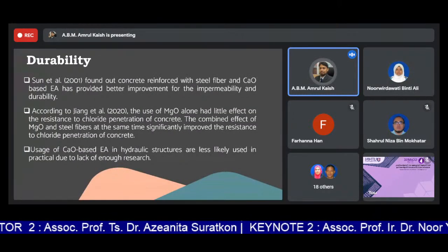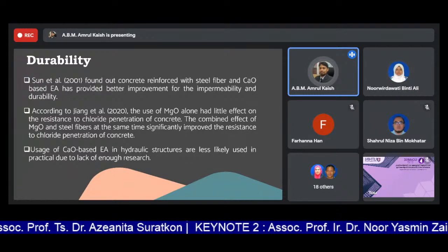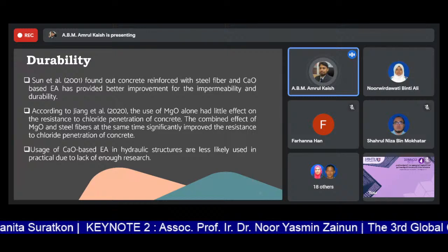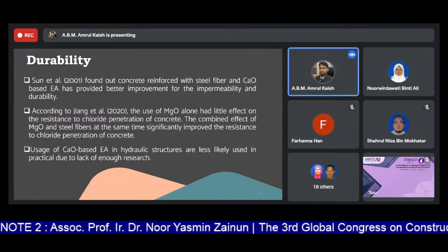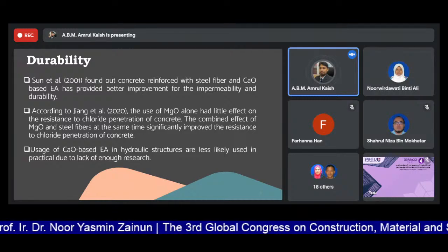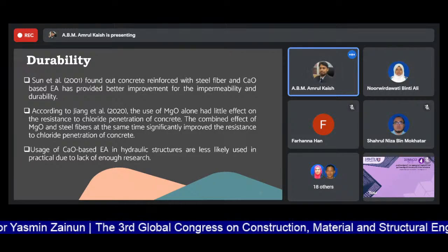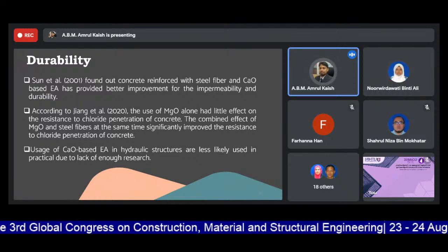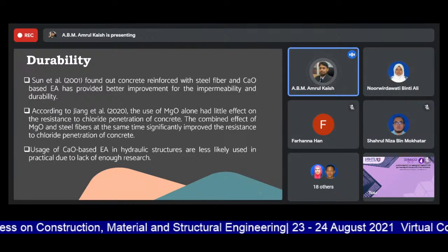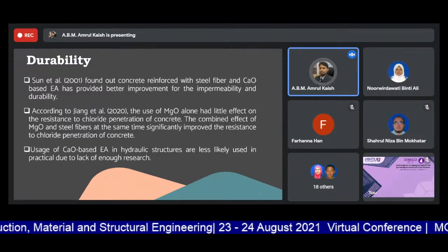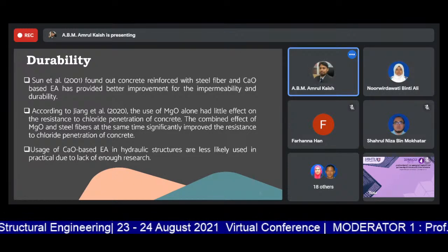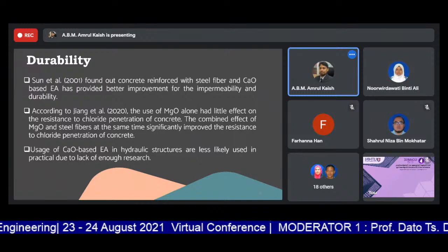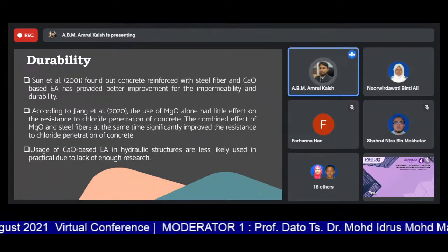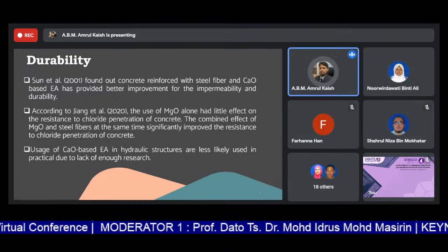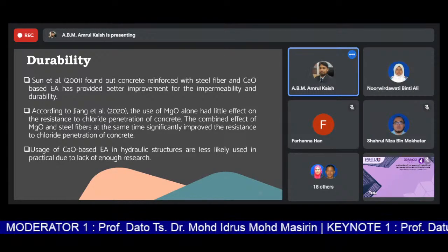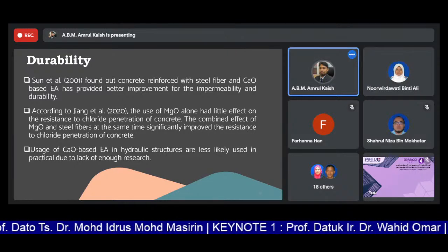And the durability, one study found that the reinforced concrete with steel fiber and calcium oxide based expansive agent has provided a better improvement in the permeability and the durability of the concrete. And according to Jiang et al. (2020), the use of magnesium oxide alone had little effect on the resistance to chloride penetration of the concrete. The combined effect of the magnesium oxide and steel fibers at the same time significantly improved the resistance to chloride penetration of the concrete. And also the use of calcium oxide based EA in hydraulic structures is less likely in practice due to the lack of enough research.